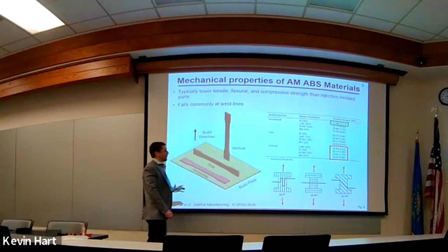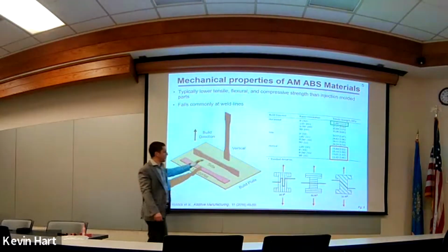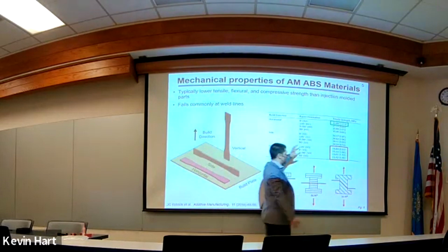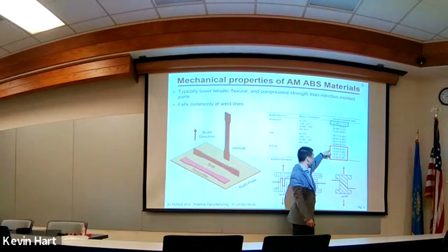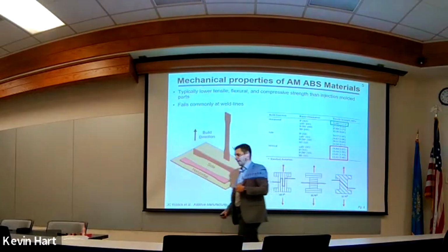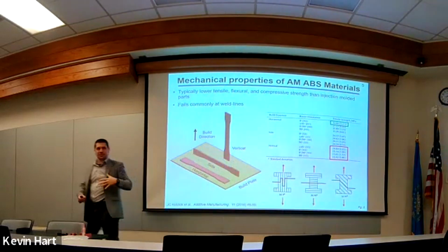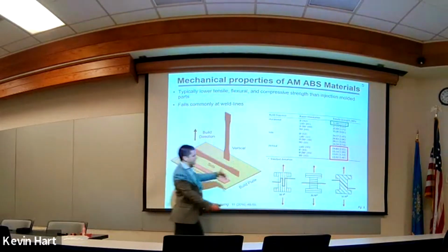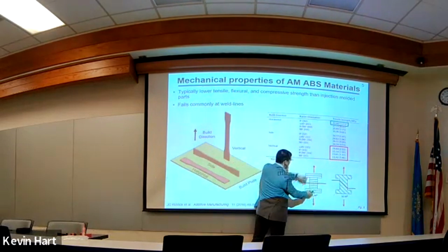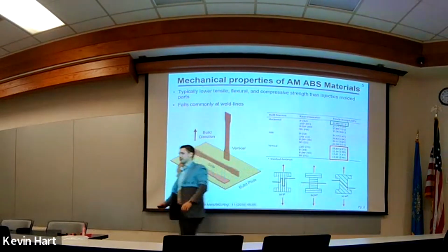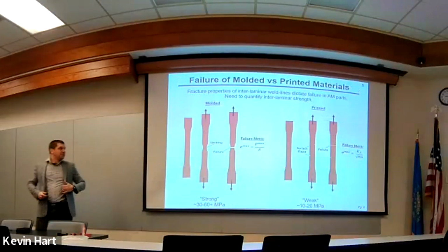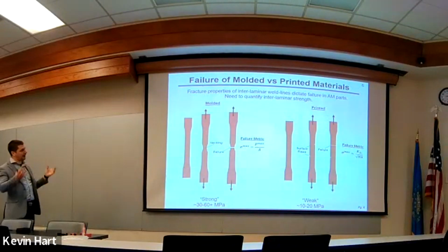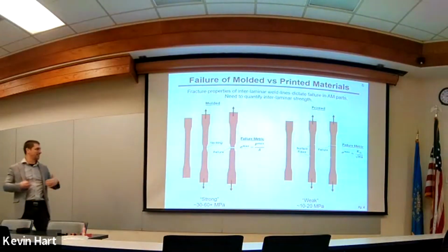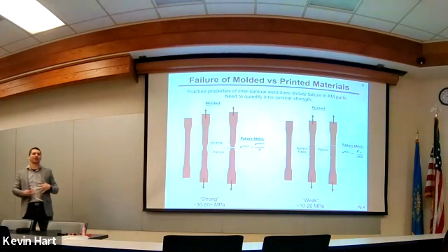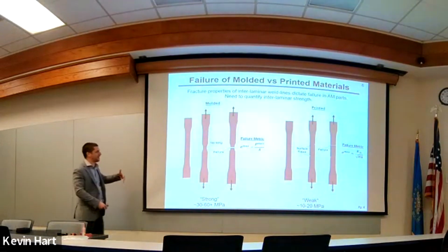This person tested at about 32 MPa, but if you go in this vertical orientation, there's some dependency on the rastering directions that you choose, but anywhere from 12 to 20 MPa. So significant reductions when you start loading in this direction where the weld lines are perpendicular to the direction of loading, okay? So this is not something that I observed myself for the first time. It's pretty obvious to understand this idea.